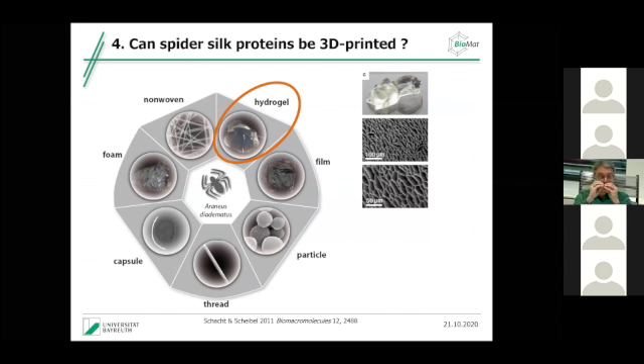We have some engineering in the silk that allows us to attract human cells, specifically the cardiomyocytes. We know this works in 2D. The next step is to go 3D. And for that, we have to go now to silk hydrogels. And this has been shown almost 10 years ago, that we can make hydrogels out of spider silk. And this is just some SEM pictures to have a glance inside, and we see a porous structure, and the pores are big enough to actually harbor human cells. So we thought these hydrogels are very well suited.